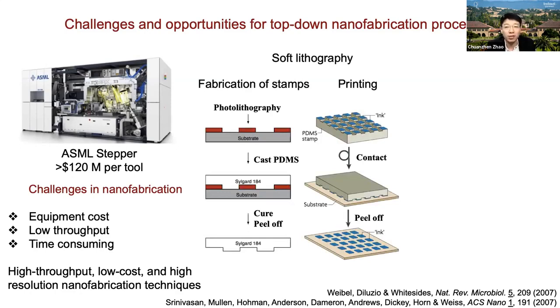Alternatively, soft lithography emerged as a promising tool for micro and nanofabrication. Soft lithography uses polymer stamps, generally made of polydimethylsiloxane, PDMS, to transfer and print micro and nanoscale features. This technique provides an alternative approach for nanolithography with the advantages of high throughput and also low cost. An example in soft lithography is microcontact printing. A typical microcontact printing process includes two steps, the fabrication of the stamps and the printing. For printing, the PDMS stamp will be immersed with an ink solution. For example, it can be an alkyl molecule, and then it can be flipped over and brought into contact with the surface. And then a covalent bond will form at the contact area to make the chemical pattern of interest.